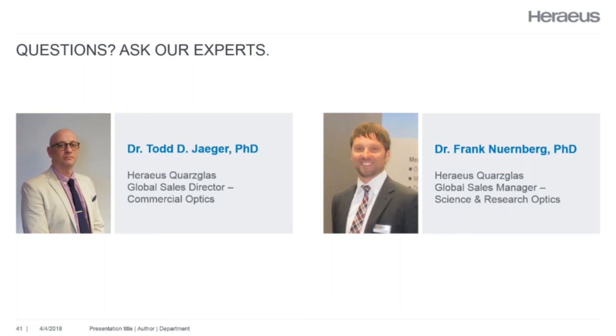So in principle, it is just ray tracing. If you have a window, you're looking straight through the thickness of an optic. Then it is important that you have the material homogenized in that one direction. And this is for all materials, as Todd already mentioned, with a 2 at the end. Typical applications are windows, thin debris shields, or lenses with a big radius. So that means a long focal length, because in that case, the deviation of the ray tracing in the material is small compared to the typical transmission direction, which is in functional direction.